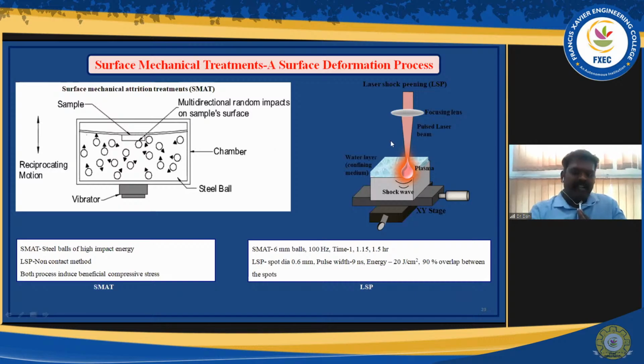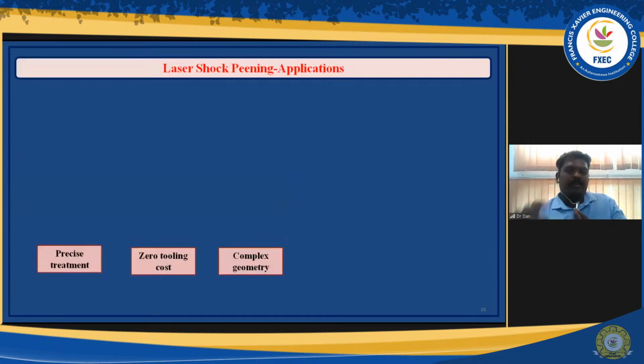Another case here I showed is laser shock peening. Laser shock peening is nothing but they use a pulsed laser beam to make high energy plasma. That high energy plasma will induce a shock wave inside your material. That will lead to grain refinement. Also that will give residual compressive stress, which is really beneficial to improve the fatigue life of your material. Okay, so that's what I want to say.